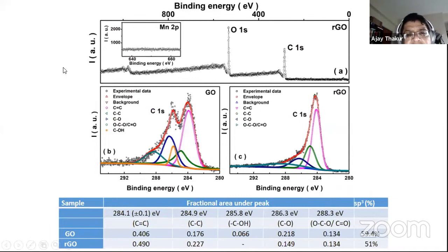So here I would take about half a minute to a minute to tell you a few things. One of the important parts is to look at this window of binding energies from 640 to 660 eV. This is the window within which Mn 2p peaks are expected. So the absence of any XPS peak in this window attests to the fact that there are no manganese residues in our samples. So that is another benefit over and above the older techniques. While being a non-explosive technique, it also did not lead to any Mn residues, and the quality of graphene oxide